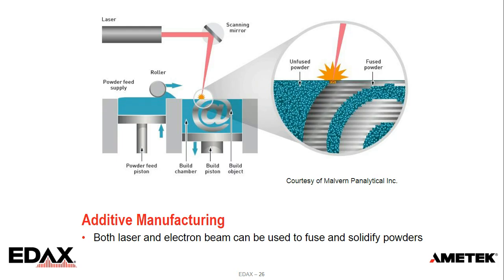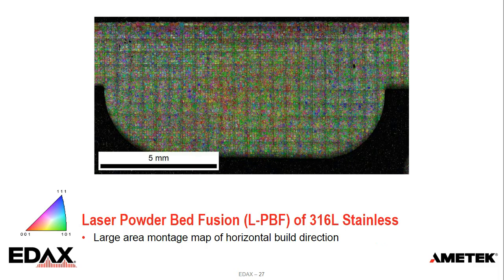And this is just an example using laser powder bed fusion. This is a 316L stainless sample. This shows the orientation map. Again, this is a large-scale montage map, but it's showing what's termed the horizontal build direction. In that case, the layers are building up towards us, so we're looking at the very top layer after the fabrication. And you can see there these greenish colors. I hope they're green. This is where my color blindness will hurt me, but to me they're a greener color.